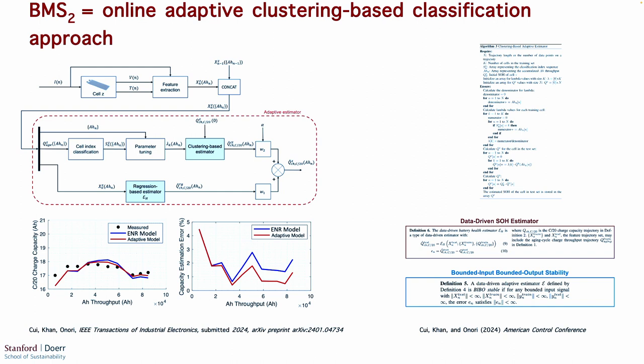And so we use an adaptive clustering-based classification approach. New data will come in, we classify the features from this new data, and we look at the closeness of these features with respect to the offline features. So eventually, this is a closed-loop system that works in real time. And what we could give as part of this work is also a guarantee of boundedness. We demonstrate analytically that there is a bounded-input, bounded-output type of stability. What that tells you is that you have a guarantee that any estimate that comes out of this observer does not diverge. That's what that means. And right now, this solution is being used by our sponsor for the deployment of second life battery systems.